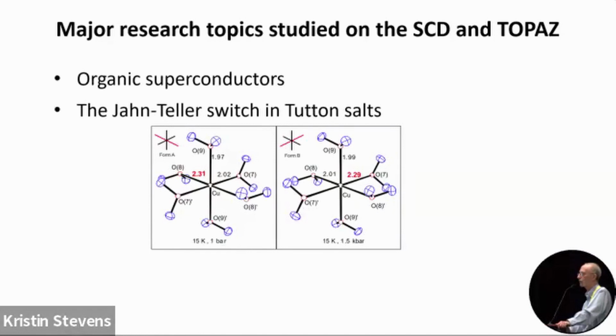And this is a cooperative event in which the hydrogen bonding network, all the copper switch at once. This was totally unexpected. And we actually had to use Multan to initially figure out what was going on. But that led to a lot of new experiments with Charlie and others.